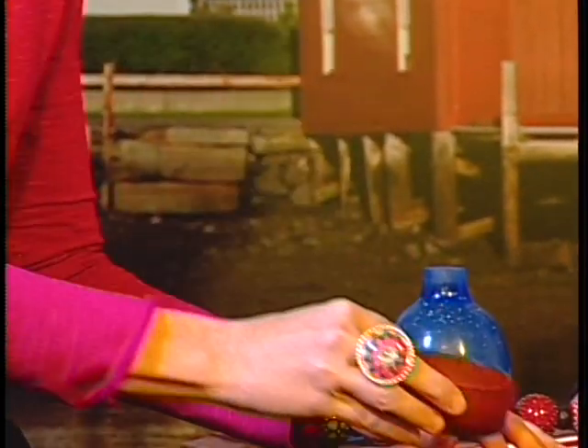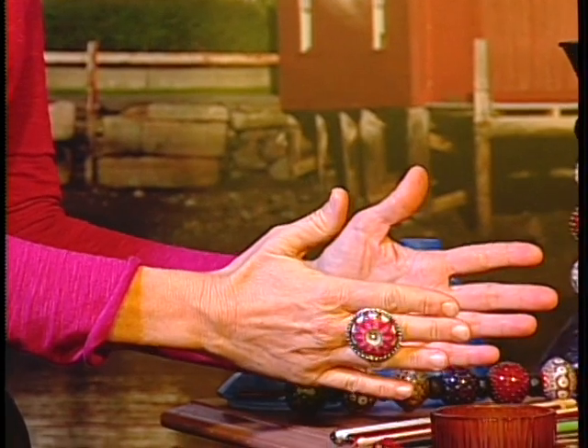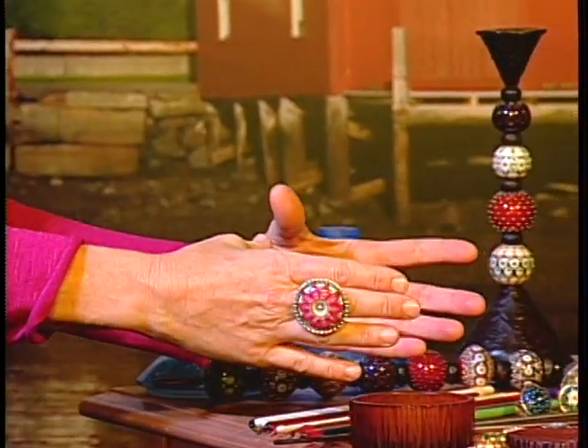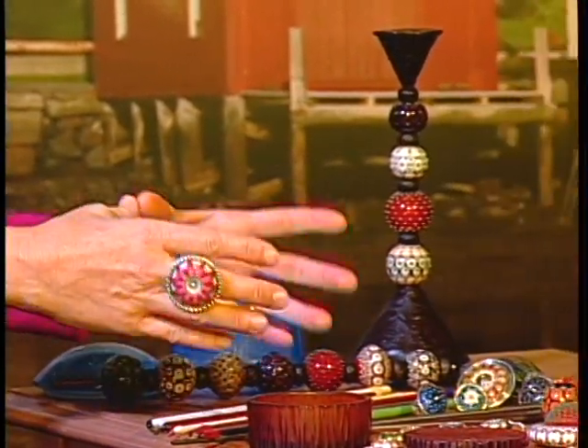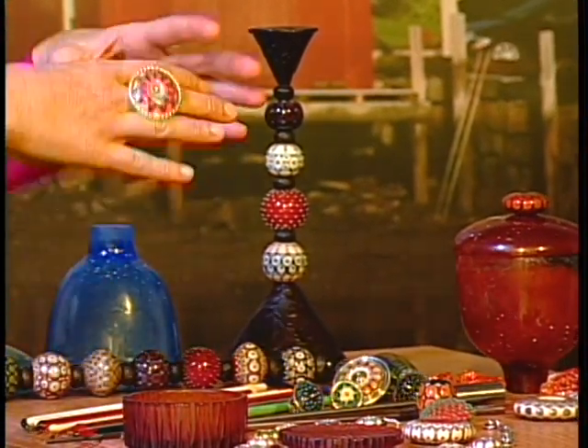After that's carved in wax, I pour over it a plaster material that also has silica in it that I can then put into the kiln later. So I pour over it this plaster material. And then I'll melt out the wax. I steam out the wax. So then if I turn over my plaster material, I have an empty negative space that used to be my object where the wax is melted out. So that's where the term lost wax comes from.